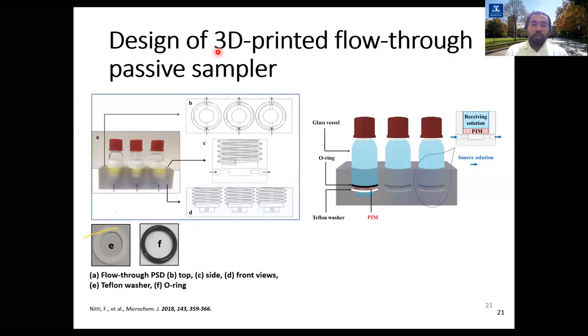So the first one, to eliminate the effect of flow pattern, we introduce what is known as a 3D printed flow through passive sampler. So we basically 3D printed the flow through device here. So this is the design. We basically have the same glass vessel. We have a flow through device. We have the Teflon washer and an O-ring. So we basically place the polymer inclusion membrane with the size of this ring. And then we place it on the chamber.